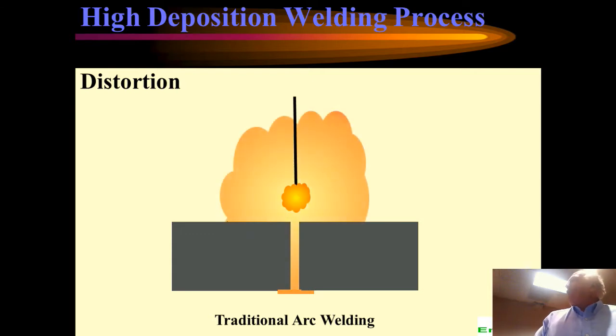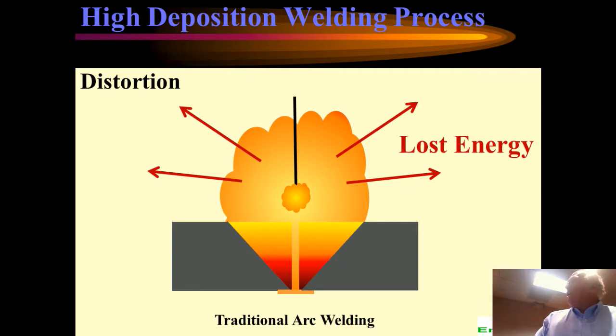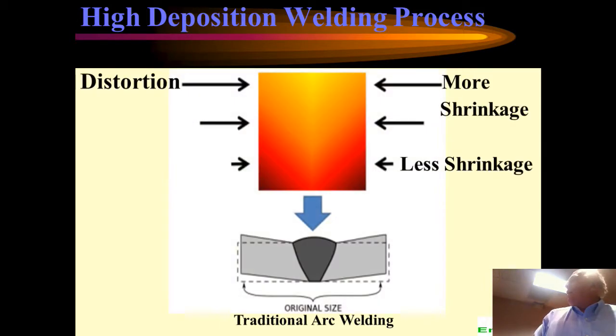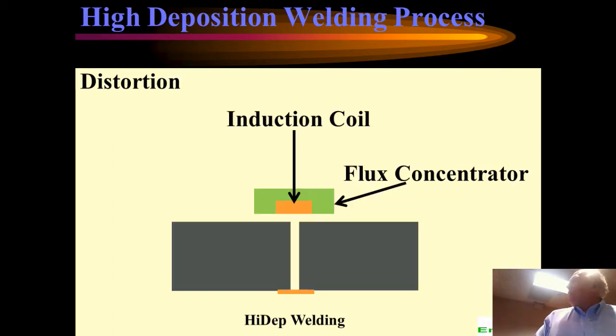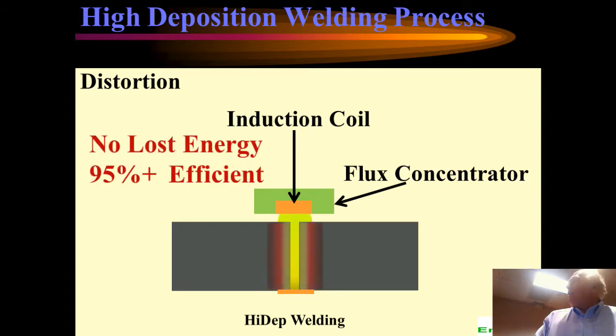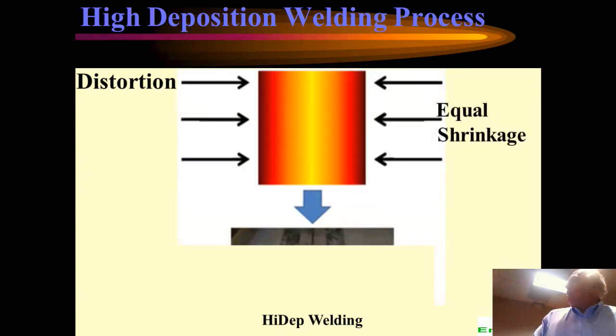So basically what happens with distortion is that when you use traditional arc welding, the arc is a giant heat radiator. So everything that's closer to the arc gets hotter, and everything that's further away is colder, and so you end up with a thermal profile that looks like that. And those arrows indicate how much shrinkage takes place, and so that's what causes the distortion. When we do our process, we turn on that induction coil, and it actually heats the metal up before the arc comes along, and it heats it very evenly. So we get an equal amount of shrinkage on the top and the bottom, and the end result is the plate sits flat.